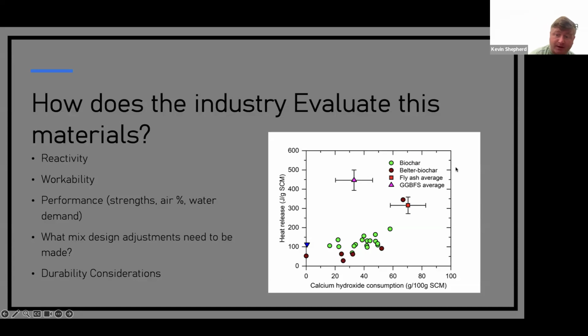We did this dot up here that does test above fly ash, in the fly ash range. It was a company, Biological Carbon, where John and I had done slow pyrolysis to a municipal solid waste from grease traps, blended it with some minerals and some other stuff that I guess could be part of my IP if I was ever able to come up with a process. But we were able to engineer that material as a biochar to react just as much as fly ash. But what was the problem with that material was the workability.